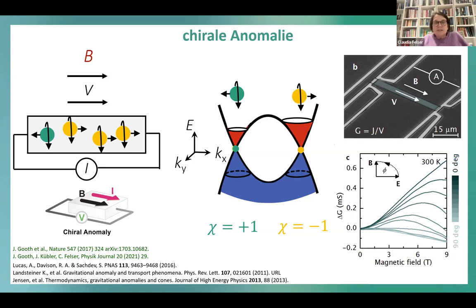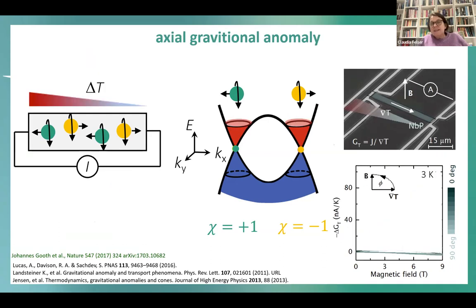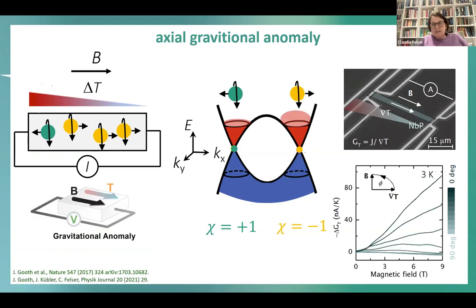And then you can do the same in a thermoelectric experiment. Again, you have the same number of green and yellow atoms. So here you also measure with the magnetic field perpendicular, then you switch the magnetic field direction, and you also see a giant effect. Here on the right side at the bottom, everything is parallel to the B field, then you see this, and this was a gravitational anomaly.